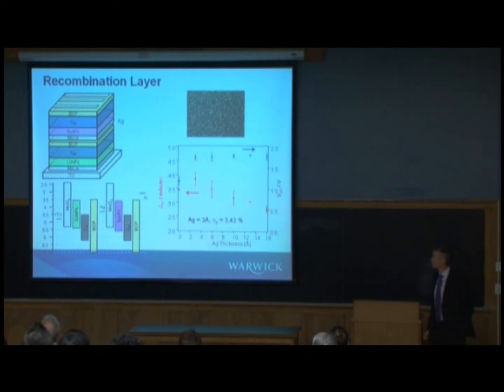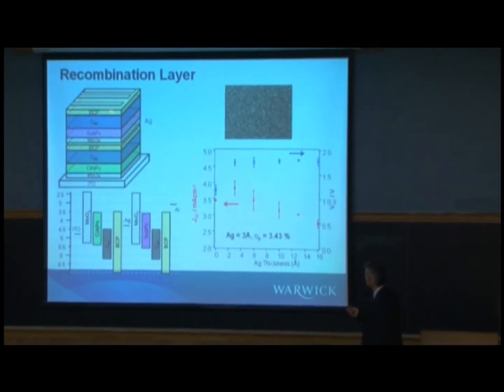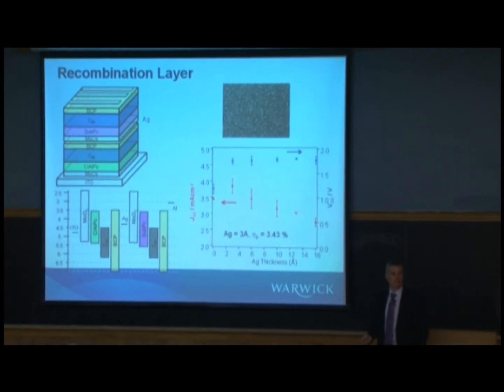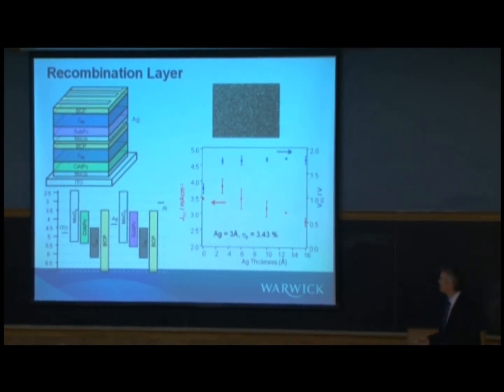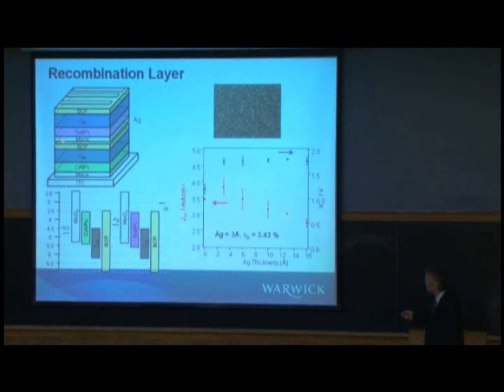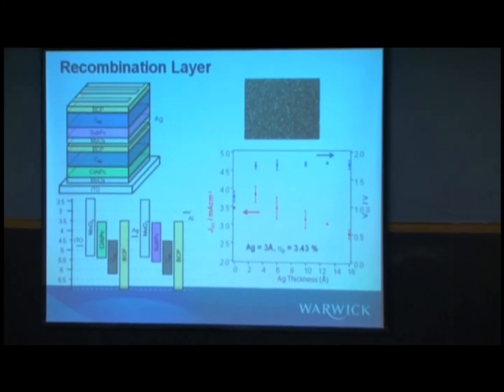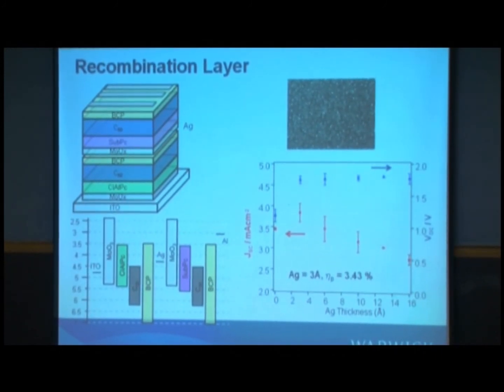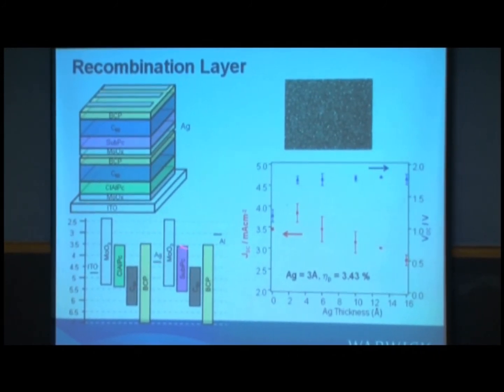This is just to show the recombination layer. This is some work. So again, two subcells. So these are quite complicated structures now in terms of the energetics. Recombination layer here in the middle. We're using silver particles. Deposit silver, it's just evaporated. And this just shows how the device characteristics change with silver coverage.